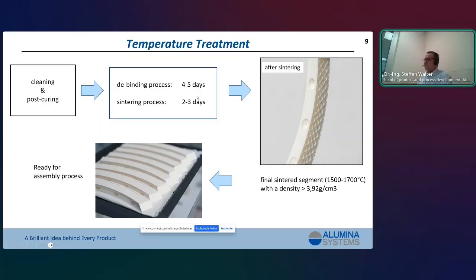Then you have a material which is first debinded, and then the sintering process has to follow, which has to be very slow as well. Such a sintering process could take 2 to 3 days as well. But after that, you have here on the right picture a segment after the sintering process, with a density, so this is pure alumina 99.9 material with a density of 3.92.